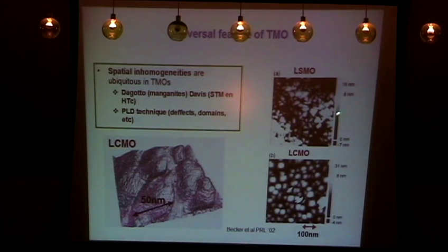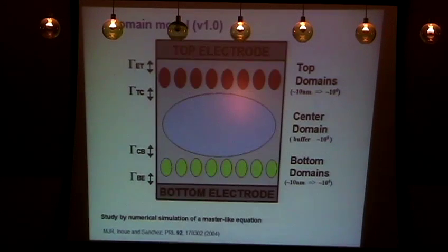AFM pictures show that the system has a natural phase separation between insulating regions, which are the dark regions there, and more conductive regions, which are the white regions in the middle. So you see that inhomogeneity plays quite an important role, and that is one of the things that we want to keep in order to try to come up with a model.